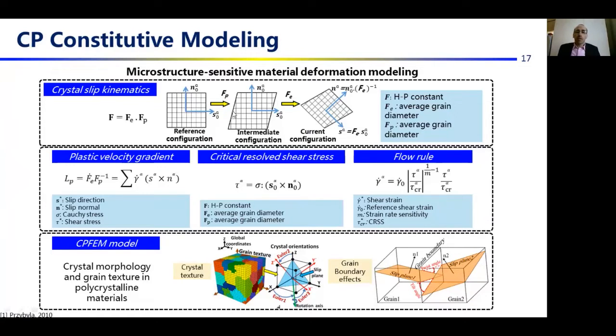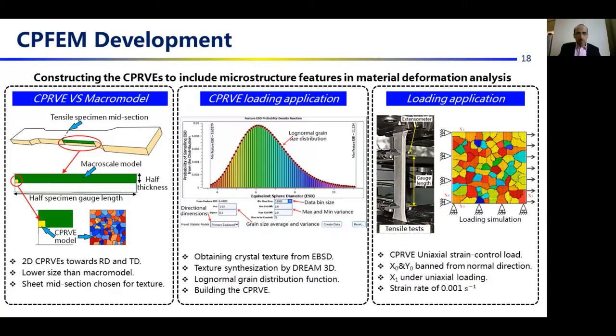CP modeling includes considering the crystal lattice rotation and slip as the source of material elastic plastic deformation. It calculates the plastic velocity gradient, critical resolved shear stress, which is the slip strength, and flow rule, which defines the slip shear strain rate. And the CPFEM model includes the crystal texture and grain boundary effects in the microstructure-sensitive model.